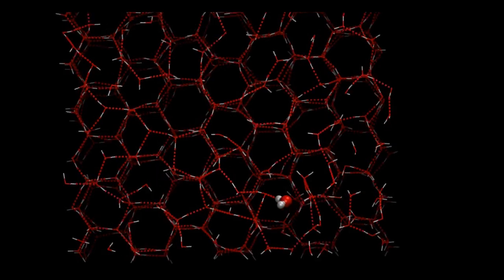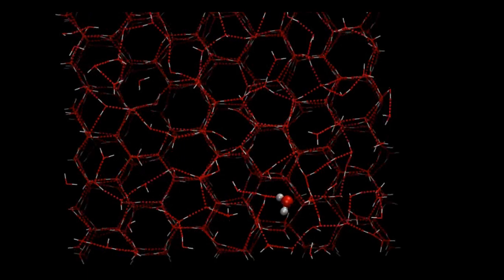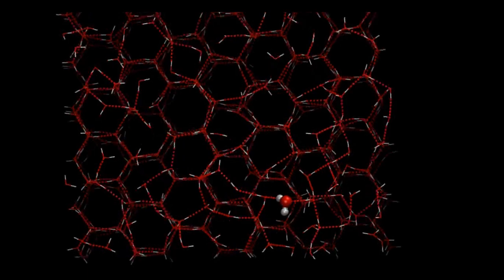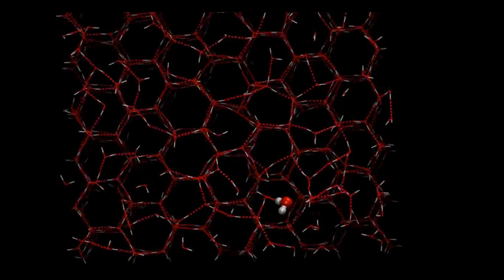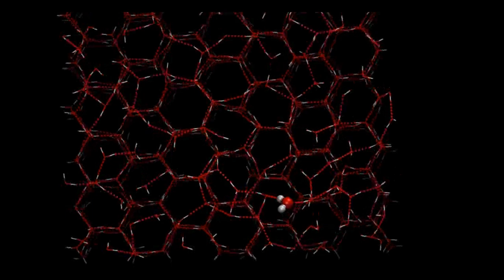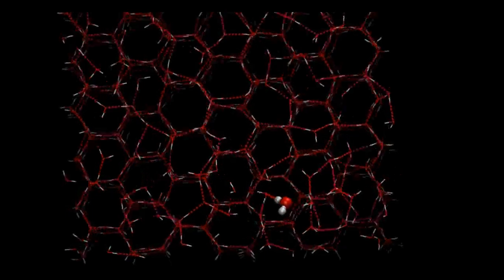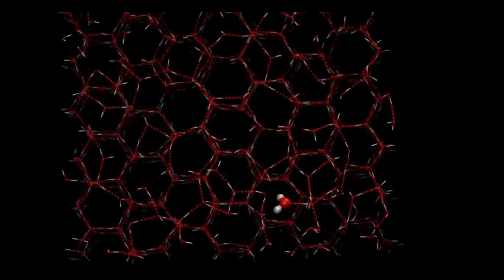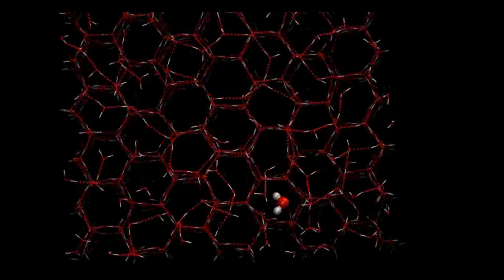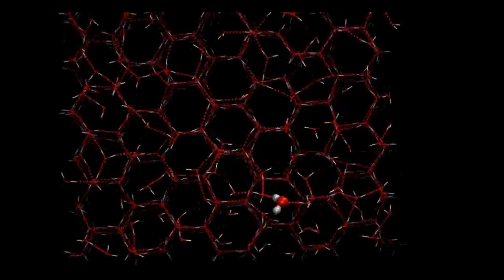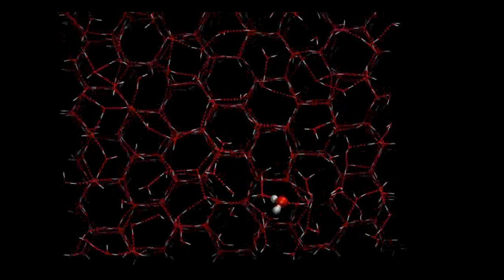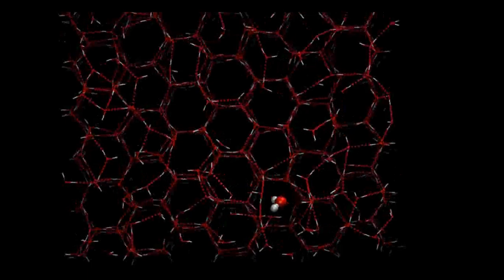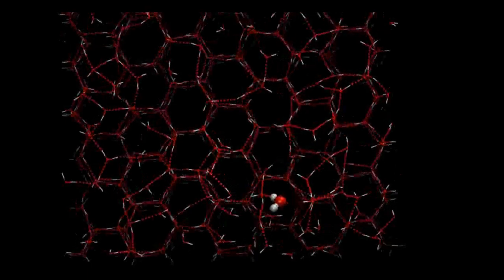A recent study has proposed that there is one molecular layer of mobile water at the surface of ice that lubricates the contact. This simulation shows a water molecule that diffuses over the ice surface in a rolling motion through exchange of the hydrogen bond partner. This occurs by breaking the hydrogen bonds of the topmost water molecules, which happens more frequently as the temperature increases. So, we expect ice to be more slippery at temperatures closer to melting.